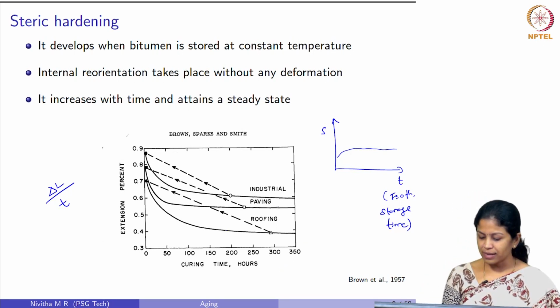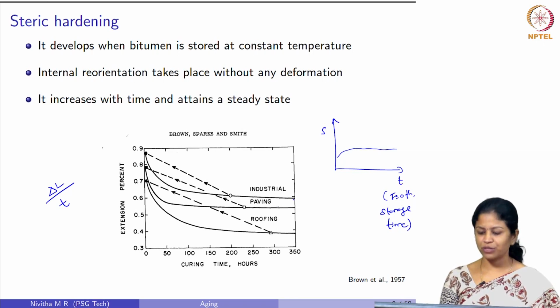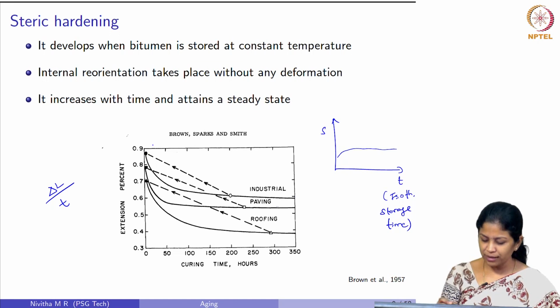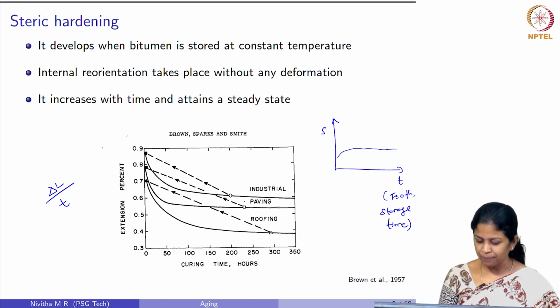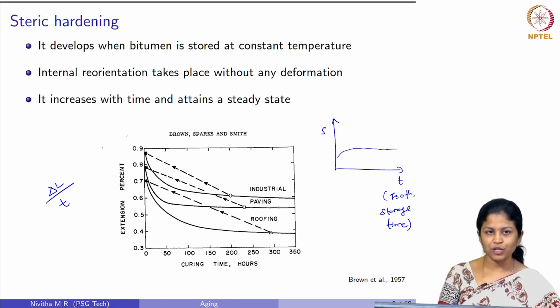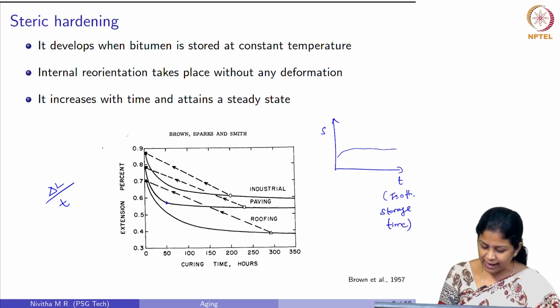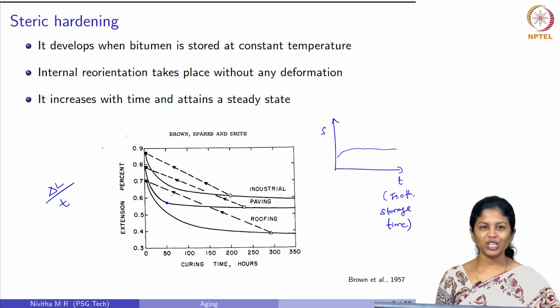What they have seen is, you can see first the solid line which is given here. This solid line shows that, let us take paving grade bitumen, initially the extension percentage is 0.8, but after we cure it for some amount of time, say for example for 50 hours, we see that it has reduced to less than 0.6 percent, right.